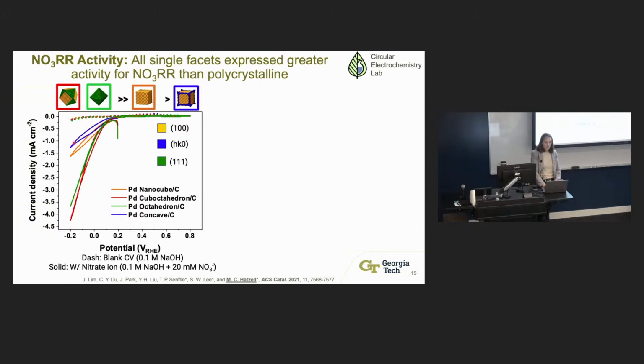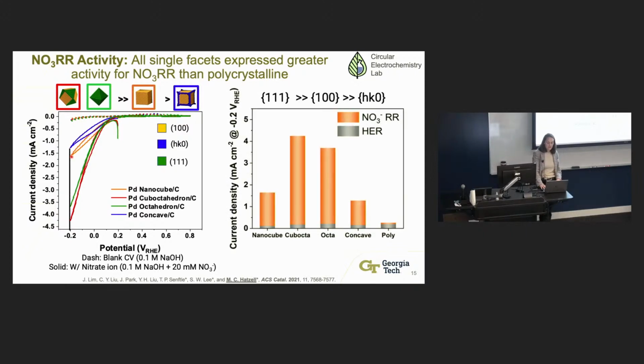And so what you can see first off is that there is significant difference in the catalytic activity as you change the nanocrystal shape. I will say the surface area is the same in all of these cells. And so the differences in the current is really just due to the different exposed facets of these nanocrystals. And what we see here is that the cubooctahedron and the octahedron had the highest current density, whereas the concave and the nanocube had the lowest current density. And so this is another way that we can look at that, where you can decouple the current that's going to that hydrogen reaction versus the current that is going to nitrate reduction.